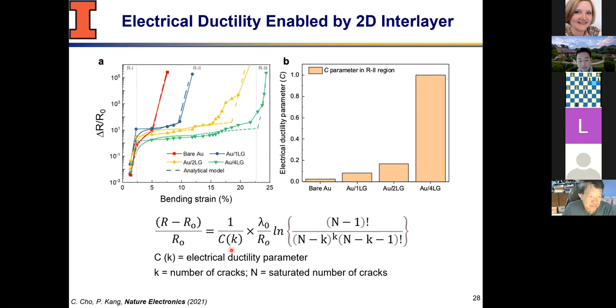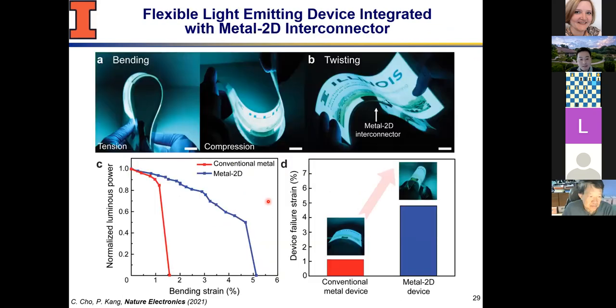And one parameter that we can find with this exercise is, as we change the number of graphene layers from 1 to 4, our fitting parameter, the electrical ductility parameter, actually increases. So compared to one layer, 4 layers is about 10 times more. That's why we're seeing this enhanced stability of electrical resistance that can be quantitatively fit by this kind of correlation. So that helps us to really understand and also perhaps optimize the number of layers. How many layers are good? We've done a little bit of analysis on that as well, but I probably didn't bring it here.